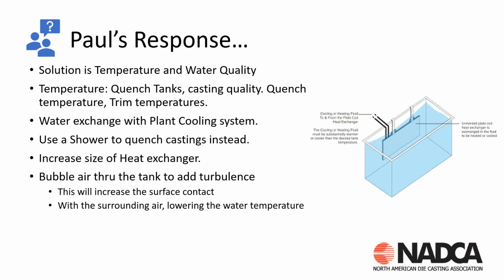And frankly, for several years, I ran a casting. It was a 15-pound gate running 90 shots an hour with ejection temperatures right around 550 degrees Fahrenheit. With a standard quench tank, I had a very similar setup with a heat exchanger on the tank, and frankly, it was only 2 to 3 hours after starting the production operation that the water would be near boiling.